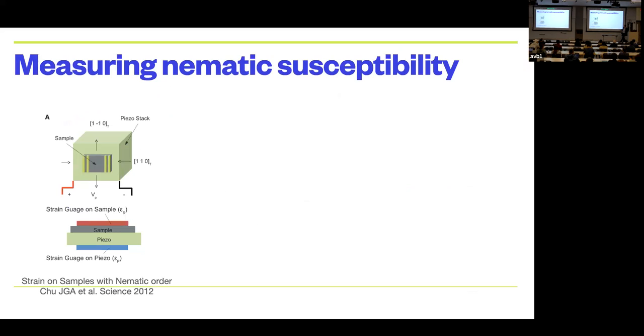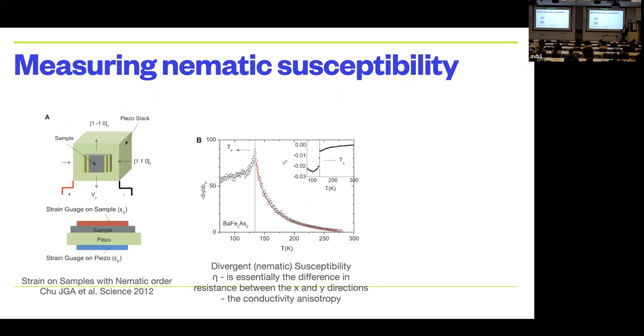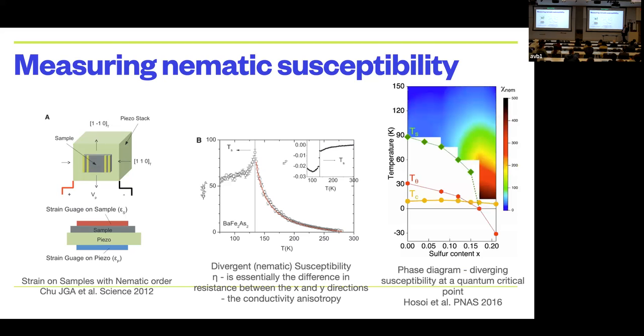So what did we do? We strained the systems, here on a piezo stack. We looked at how this parameter was responding as a function of temperature. You can see this divergence. This basically shows you that it really looks like a susceptibility that goes like 1 over T, and that diverges right at the critical temperature itself. And other people followed up on this work and mapped this susceptibility as a function of, in this case, doping or sulfur content in these materials. And you can see that this color plot basically shows the size of this divergence in the susceptibility. And right near the critical point, namely where that transition goes to 0, where the order parameter disappears, where the interactions driving that broken symmetry disappear, that's somehow where you have the largest response, the largest susceptibility to that external way of breaking that symmetry.